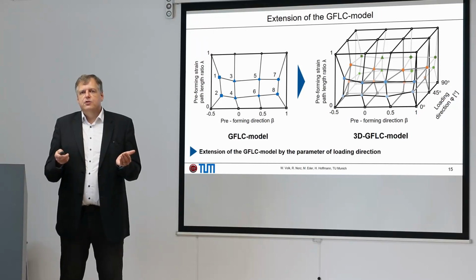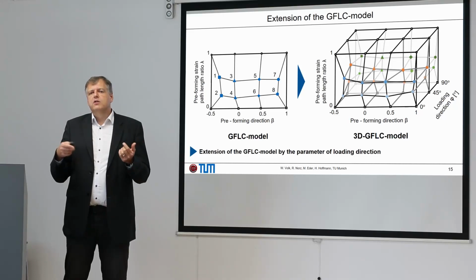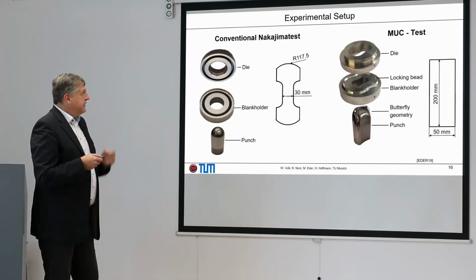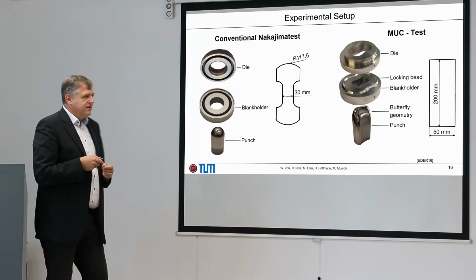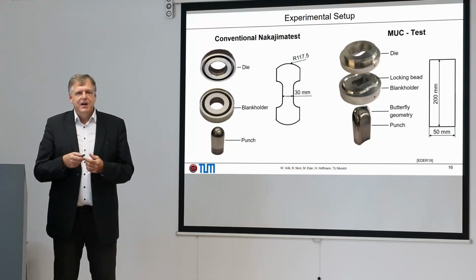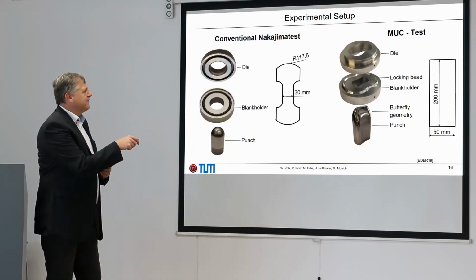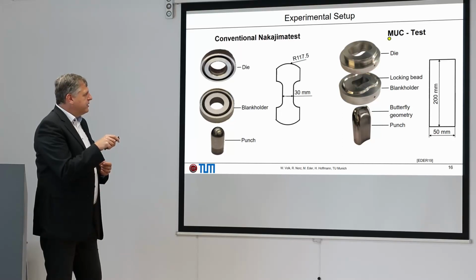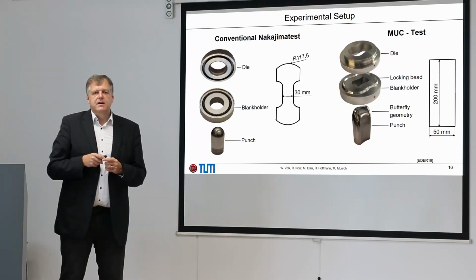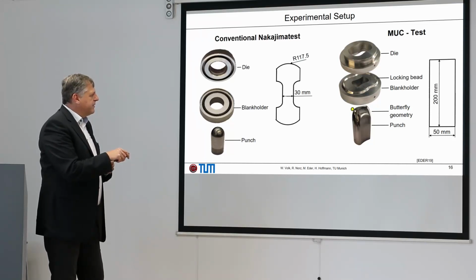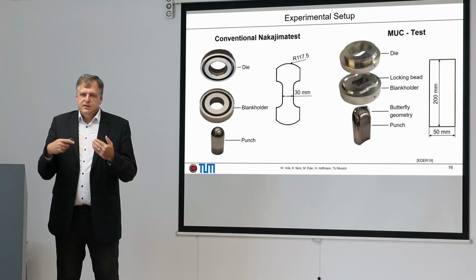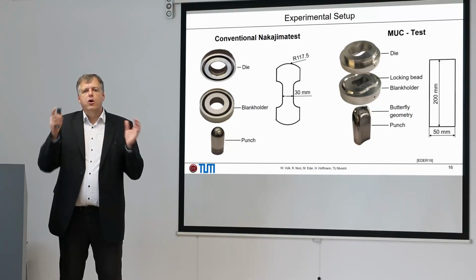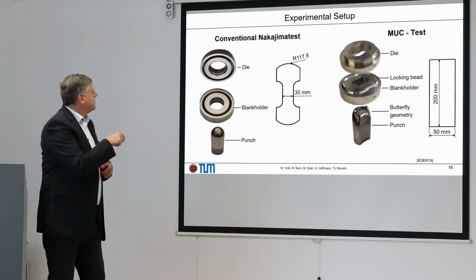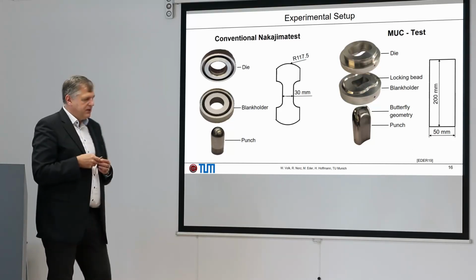And when we want to validate this, you should have also a boundary value problem, which is more close to industrial applications. And this is done in this paper by our so-called MUC test. Of course, it's a similarity to our town Munich, but we say it's material under control, and that's the combination of MUC. The difference between the MUC test with respect to the Nakajima test, as you can see here, we have a changed binder, a so-called butterfly binder, and punch, also where we have different radii and combination of strains. So there, with this boundary value problem, it's possible to have a more complex strain distribution within the specimen in comparison to the conventional Nakajima test, which you can see here.